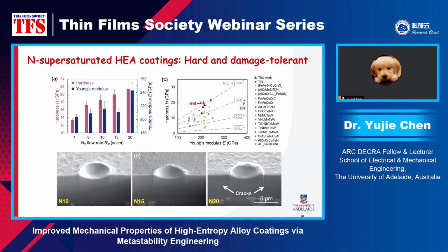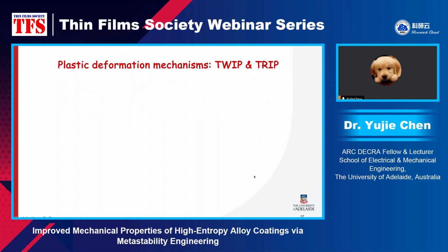But what is the deformation mechanism that governs the plasticity? How can the coating sample deform plastically with such a high nitrogen content? To understand the deformation mechanism, we compare the microstructure before and after nano-indentation. And for the FCC structure, we selected 2 samples. One is N4 with the FCC structure, the other one is N15 with both FCC and HCP structure.